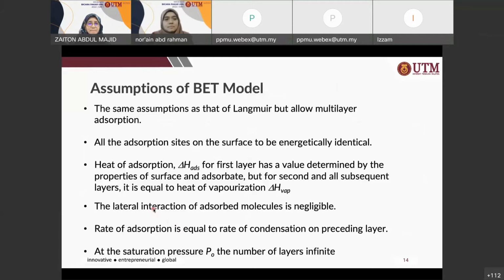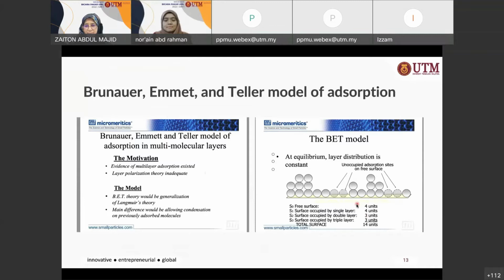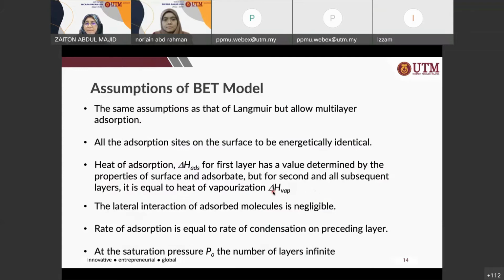Okay, so these are the assumptions. The same assumptions as those of Langmuir, but allowing multi-layer adsorption. All the adsorption sites are energetically identical, same as in the Langmuir model. Now, the heat of adsorption, delta H of adsorption, is only for the first layer. So if I can go back, yeah, the heat of adsorption is involved only between the first layer and the surface of the solid material, right? Subsequent layers are basically your delta H of vaporization.